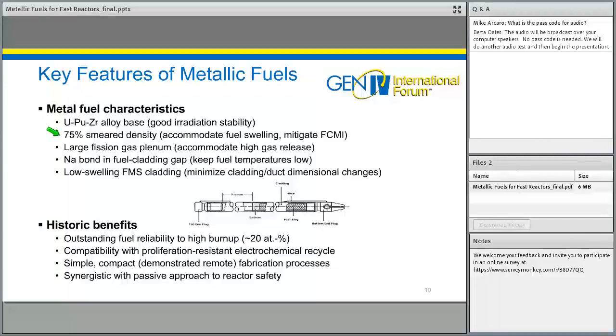Early metallic fuels used a much higher smear density and therefore weren't capable of going to very high burnup, and the early reputation of metallic fuels was that they didn't have high burnup capability. But over the years, the smear density was decreased and eventually settled in at about 75% smear density. So that provides plenty of void volume to accommodate that initial swelling. And then after that, metallic fuels can go to quite high burnup. So that was a large or a huge step forward in metallic fuel technology.